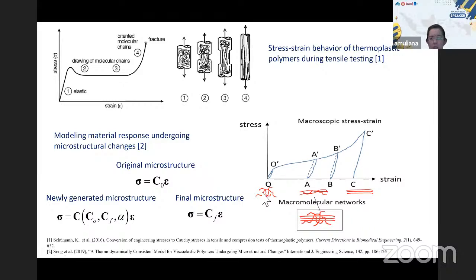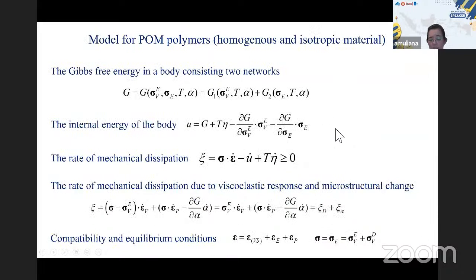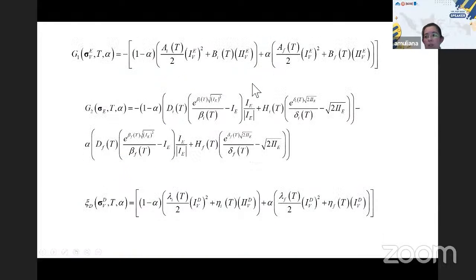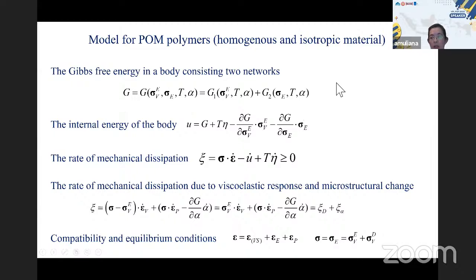So in our case, we model each microstructure as a viscoelastic material. Both the original and the final microstructure are viscoelastic. So of course the combined overall response will be viscoelastic, right? Now, how do we address this? I'm not going to go into detail with all of these equations, but the basic thing is we define the free energy. In this case, we define the Gibbs free energy that accounts for the initial microstructure and final microstructure, and also accounts for the viscoelastic effect. So we consider two networks. One network is associated with energy storing capability. The other network is associated with both energy storing and dissipation capability, right?